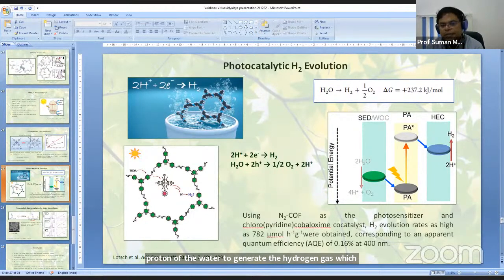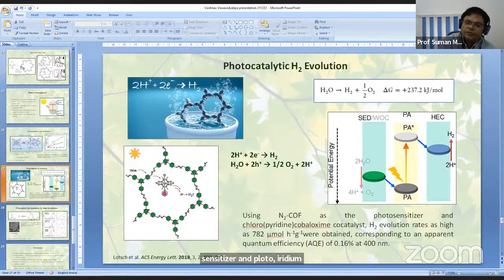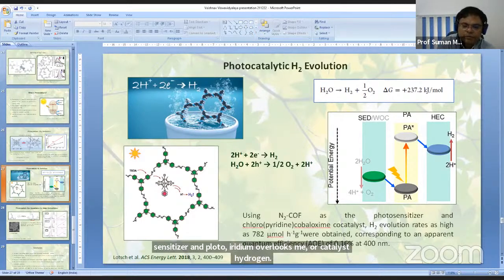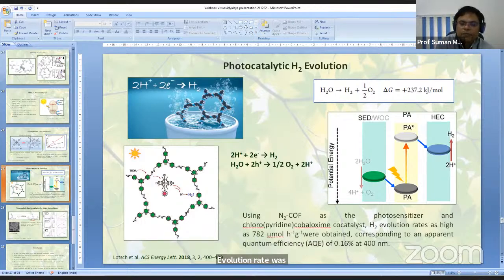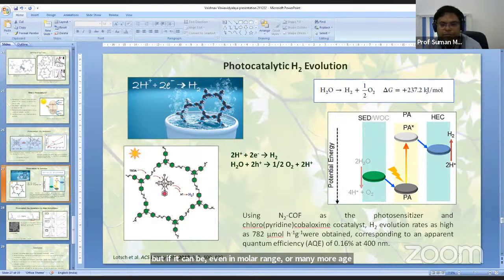So using this nitrogen-rich COF as the photosensitizer and the chloropyridine cobaloxime co-catalyst, a hydrogen evolution rate was obtained which is in the micromolar range, which is not sufficient yet. But if it can be given in molar range or millimolar range, it would be very much useful to cleave the water and get enough hydrogen, which can be used as a clean fuel for our necessary requirement.